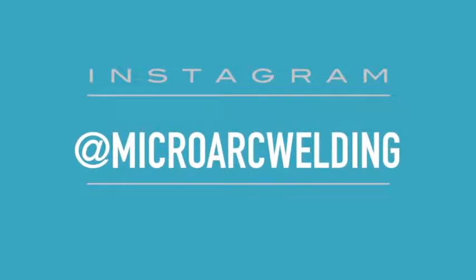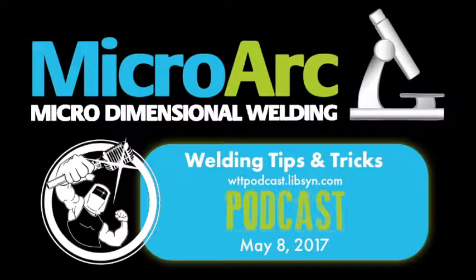I mean, we use 40,000ths stuff, but 40,000ths can't handle the amps, because when you weld a plastic injection mold, there's times in that one weld where you need 3 amps, and there's times when you need 80 amps. So I can't be switching back and forth from 40,000ths tungsten to a 16th tungsten. The 16th seems to work fine, because it can handle up to 100 amps without the heat getting diffused too much.